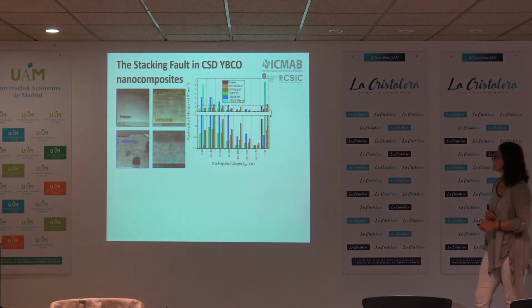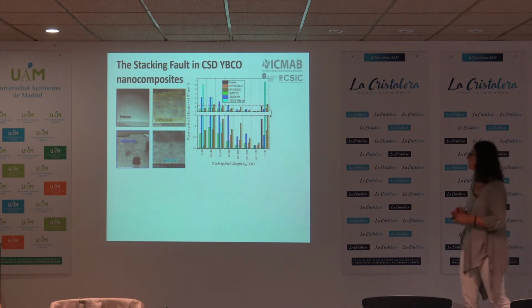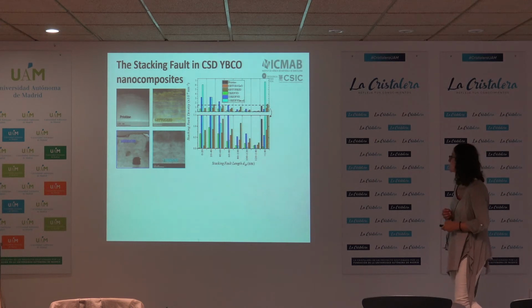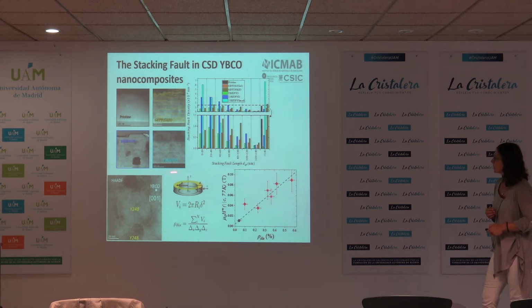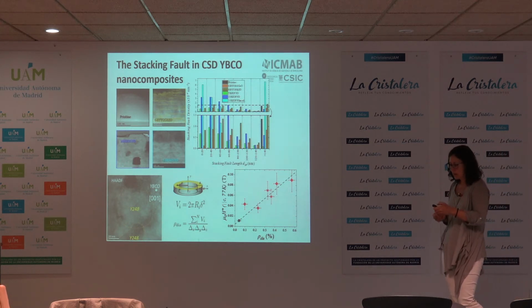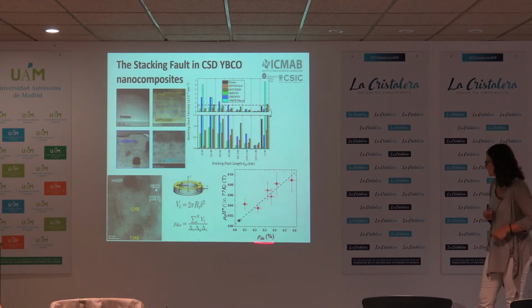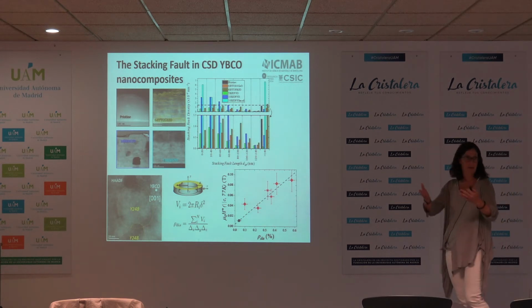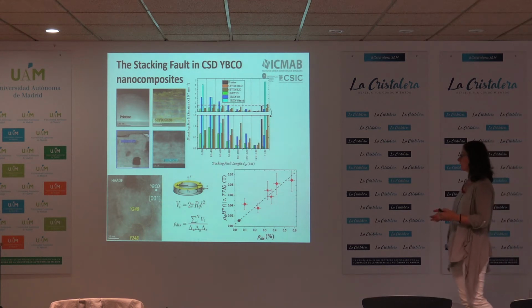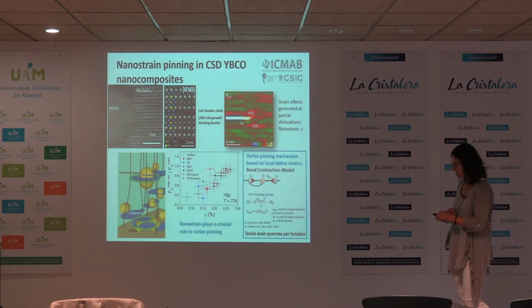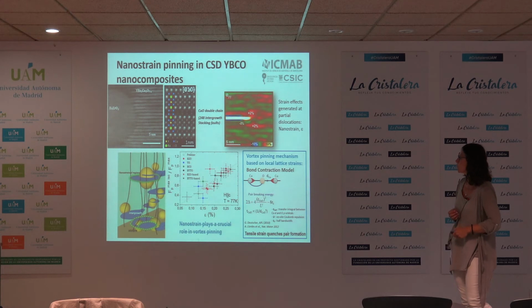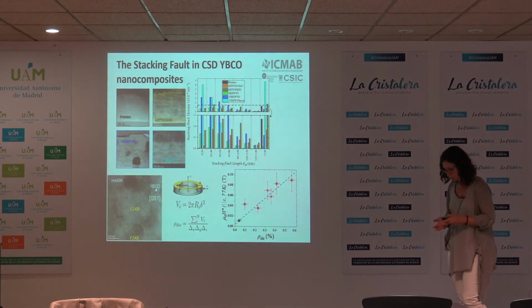In fact, if we calculate from different samples with different nanocomposites the density of these stacking faults and the length of these stacking faults, and we do statistics on this from the TEM images, then we calculate what is this area which is surrounding where the strain is, okay? Then we can see that in fact this area, which is the density of this dislocation, which is the one surrounding the stacking fault, is proportional to this edge star value that I mentioned before. So we can confirm that in fact these areas, the green areas, are the ones where the strain is accumulated and where they act as good pinning centers.